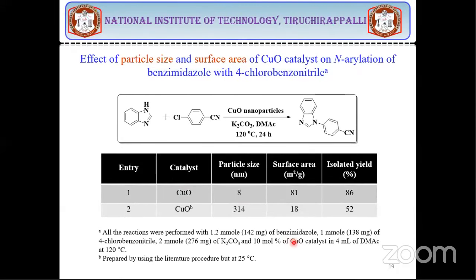Now, just to show the importance of nanoparticles in catalysis. This is the copper oxide that I have shown now. The particle size is 8 nanometer. This is the surface area we have employed in the N-arylation process. The isolated yield is 86% in this case. But now, when you employ the bulk copper oxide, you see the particle size is 314 nanometer. And of course, when the particle size is higher, the surface area will come down, it's only 18 square meters per gram.